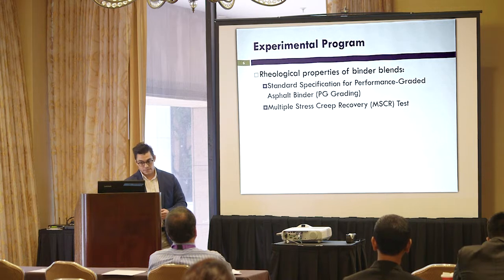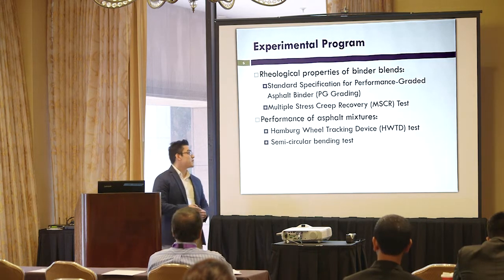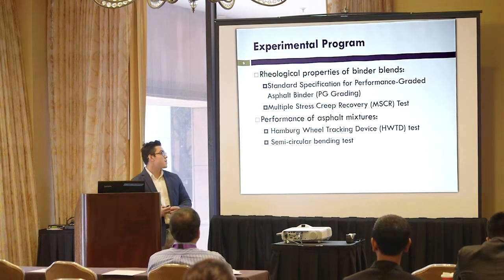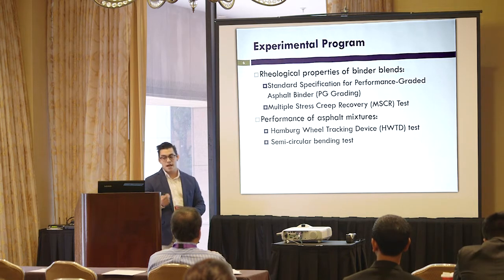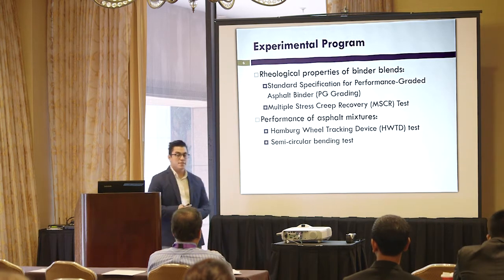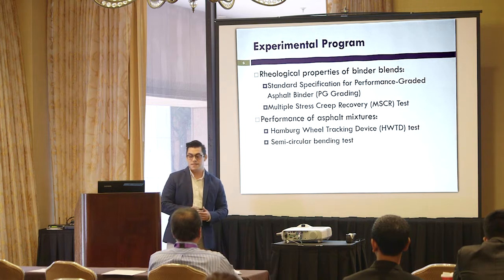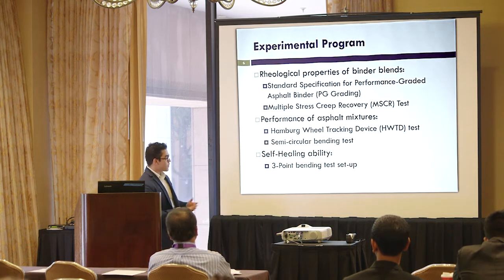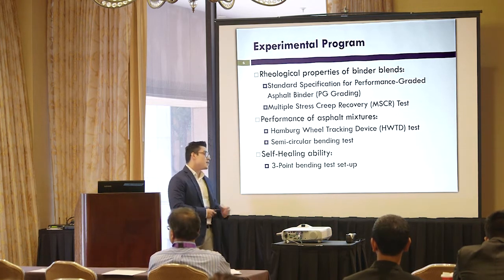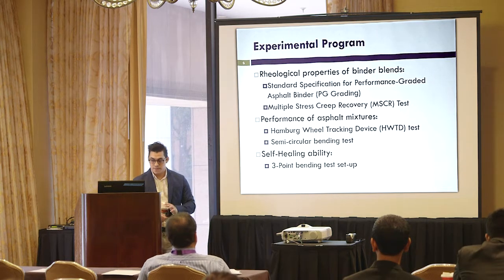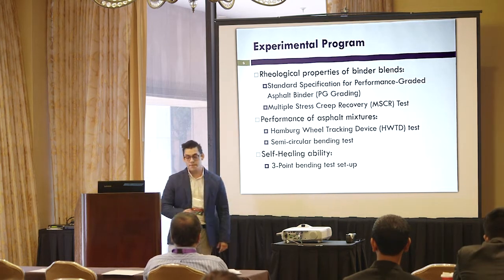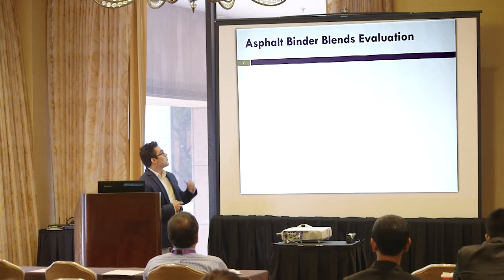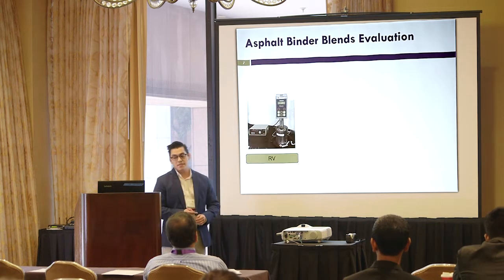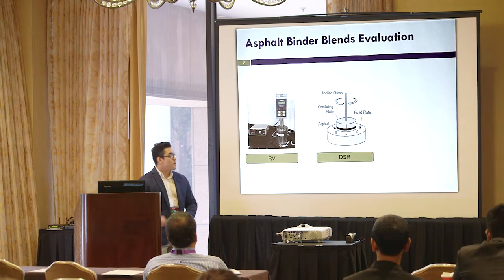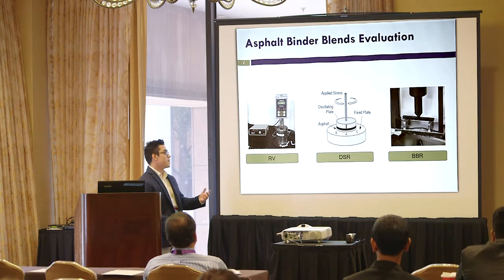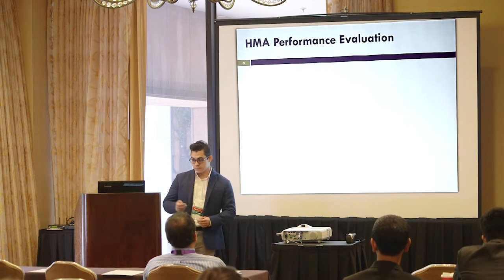The rheological properties of the binder blends were characterized by performing PG grading and MSCR tests. For the performance of the asphalt mixtures, we used the Hamburg wheel tracking device test for the high temperature performance and the semicircular bending test for the fracture resistance. And for the self-healing ability, we use a 3-point bending test, which I'm going to explain later. So for the binder blends evaluation, basically we use rotational viscometer, dynamic shear rheometer, and bending beam rheometer.